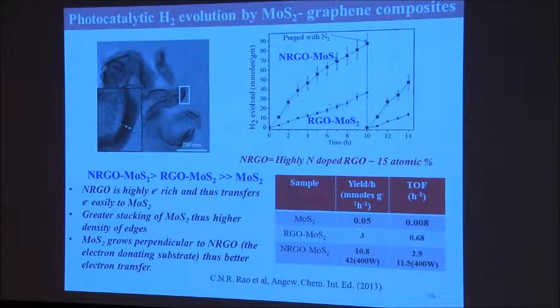But the minute I put nitrogenation, it became 10.8 just with a 400-watt lamp, or 42 millimoles per gram per hour—a very, very high hydrogen evolution with a very high turnover factor. We got that. In other words, highly nitrogenated reduced graphene oxide is a good way to produce hydrogen using molybdenum sulfide as the surface for reduction of protons.